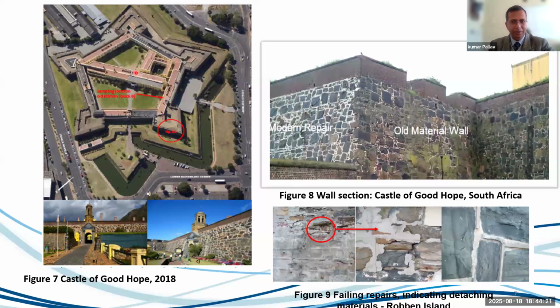So this structure was constructed in stages, with no specific property of the castle's original mortar characterized and documented. Nothing was recorded for this particular thing. So that's what we want to do, keep a record of these materials so that in any case of restoration, they can use a similar kind of mortar and treat them. So if you see on this figure 8, this is what they have treated with modern repair mortar, like they have used PPC. And this is still the old one, which you see on the right-hand side of it, right? So this has entirely changed the aesthetic of this structure.